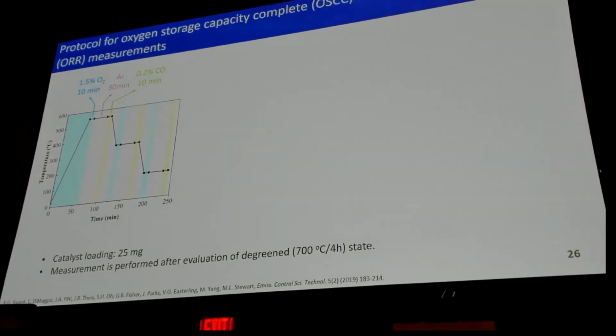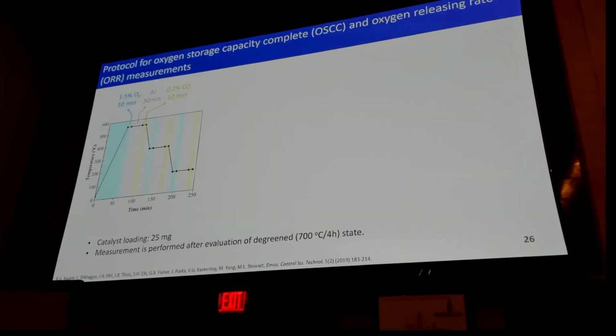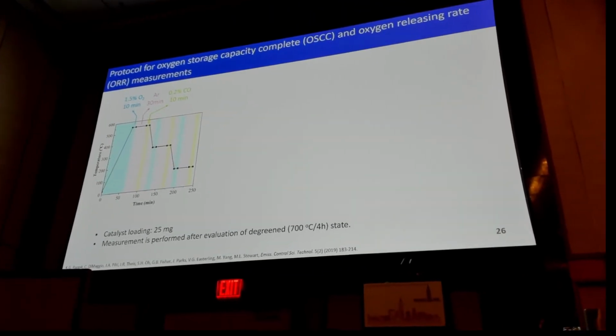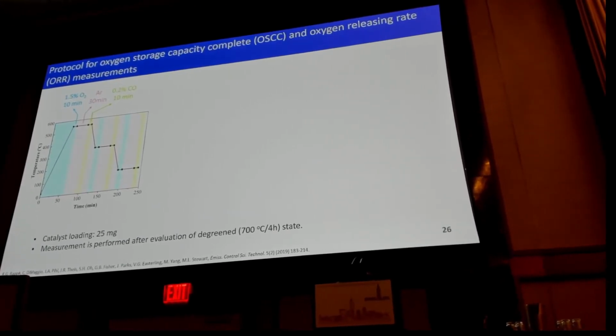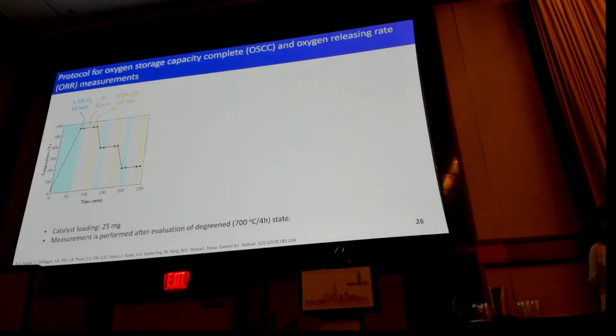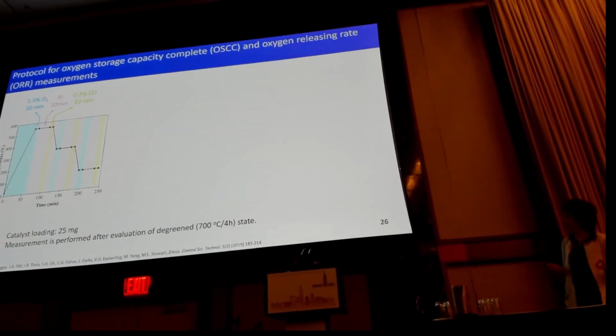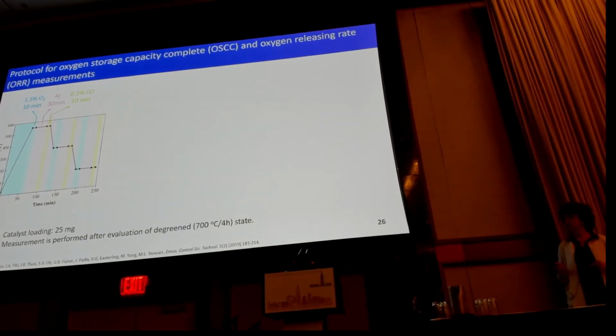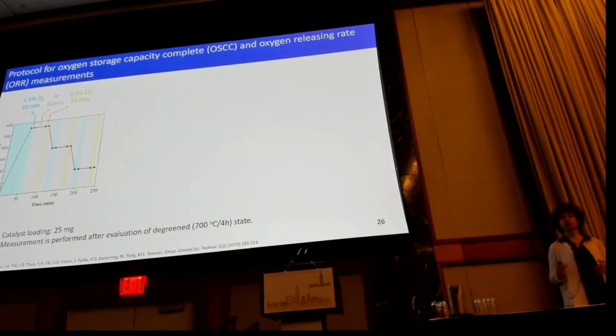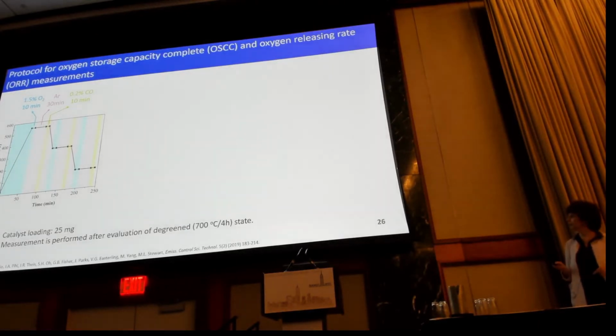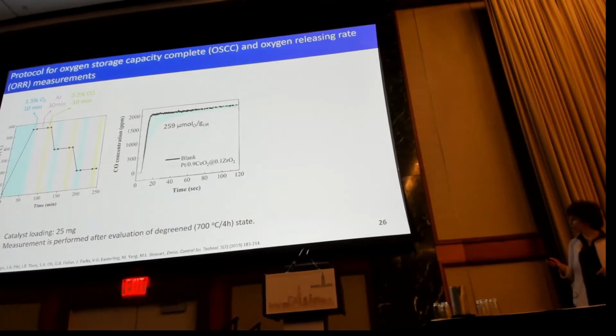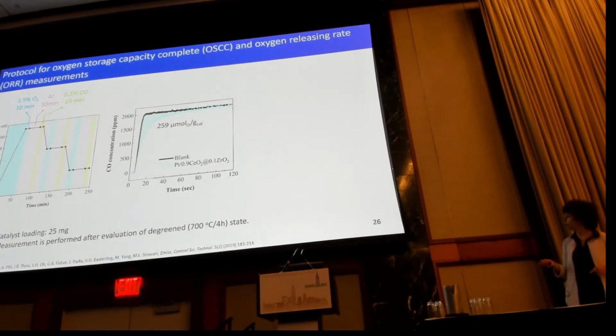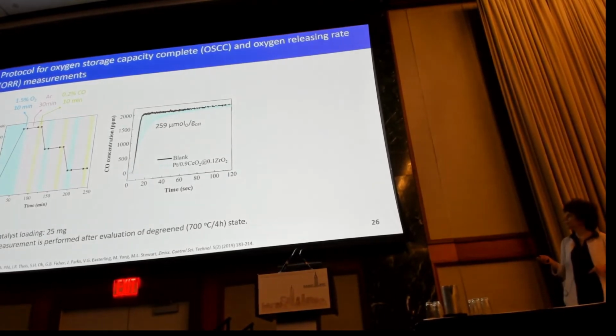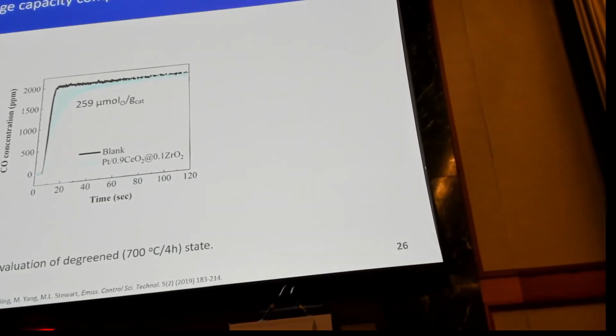So basically, we choose CO conversion because CO interacts with the lattice oxygen. The oxygen storage capacity measurements and the oxygen releasing rate measurements were conducted at three temperatures: 150, 350, and 550 degrees C. But for the purposes of this work, because we wanted this material to be active at low temperature, I'll show you only the results for 150 degrees C. Okay, so this figure here shows the CO conversion as a function of time. The black line is the blank reactor, so basically it's our baseline.